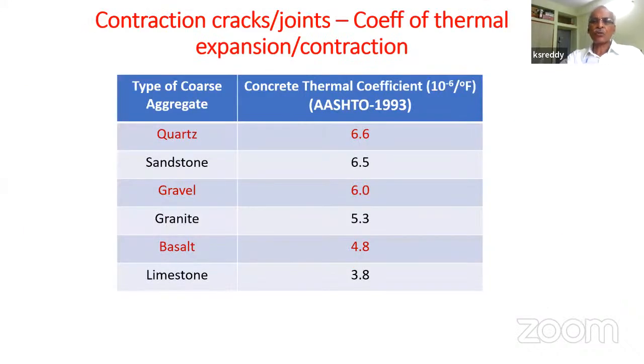So in this context, the coefficient of thermal expansion of the aggregates that we use is very significant. Suppose, as you can see, it is E alpha delta T for a simple case. Quartz can have as high an alpha value as 6.6. When compared to that, limestone can have as low as 3.8. This is very relevant. The kind of aggregates that we're using, their coefficient of thermal expansion will have an impact